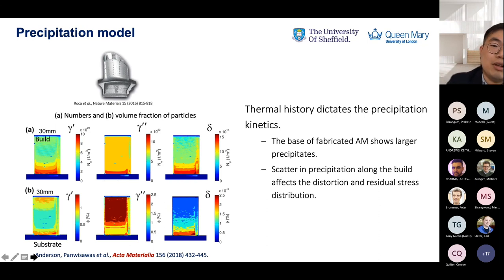This work puts a shed of light onto that. So we take a thermal history from the lower length scale information to predict the precipitation kinetics. And then you will see that there is some in the as-fabricated condition. So the precipitation wavelength can be observed here. So there's some large gamma prime, for example, this material is Inconel 718. If you want, you can follow our paper back in 2018. This is 4 or 5 years ago now. So we can actually understand why and how the build here is actually distorted and why the residual stresses are developed once we actually link this kind of result to the